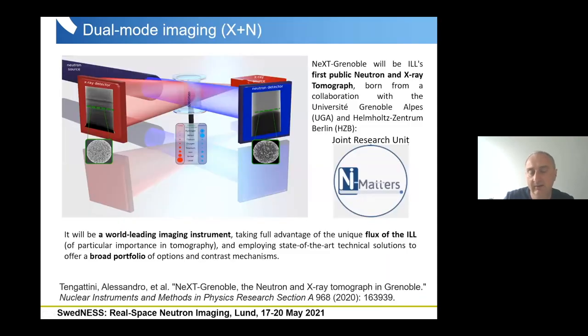So here, having high resolution is not only about observing, just using it for neutron investigations, but it is also a big advantage of combining X-ray with neutron imaging, because then we can match the same type of resolution using the two probes. The X-rays can be detected with very high resolution. And in this way, increasing the resolution for the neutron investigation, we can have complementary 3D data, which can be merged together. And in this way, we can perform dual mode imaging with much better capability, much better quality.